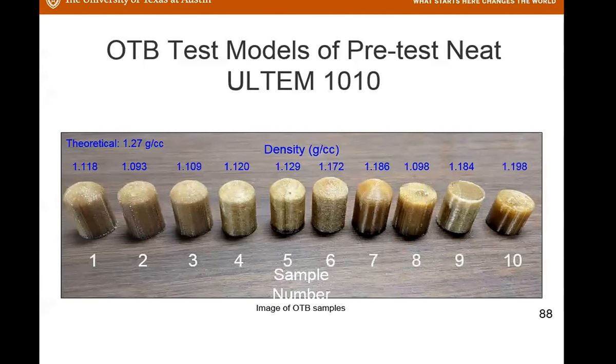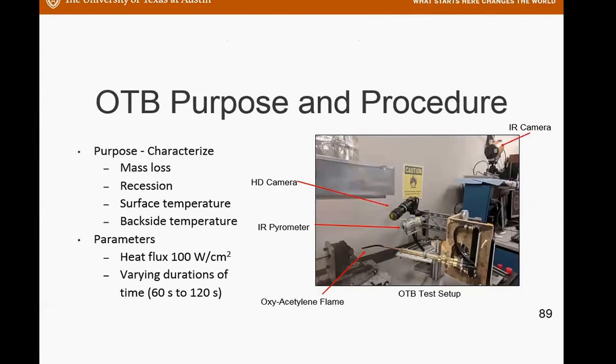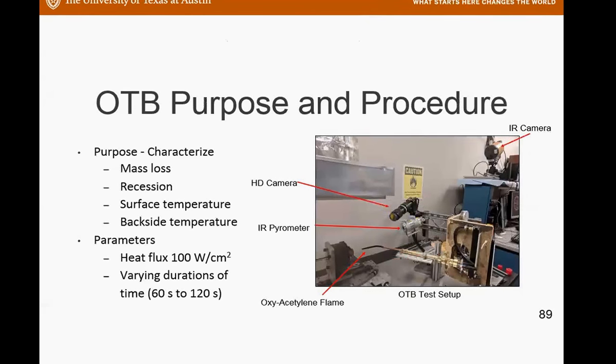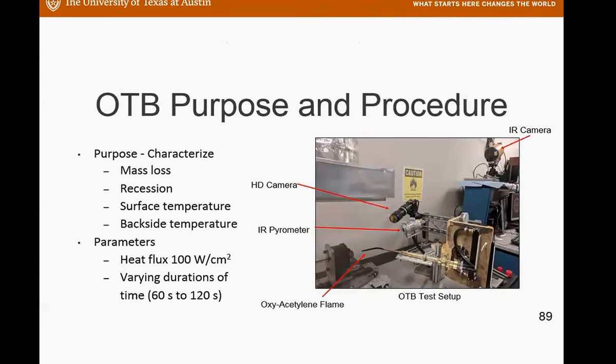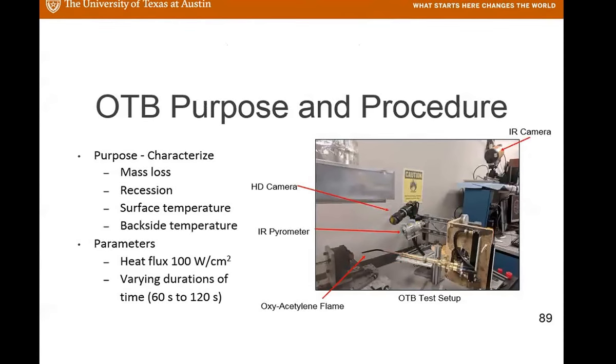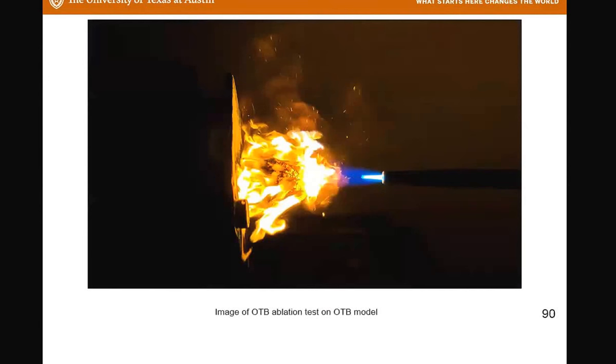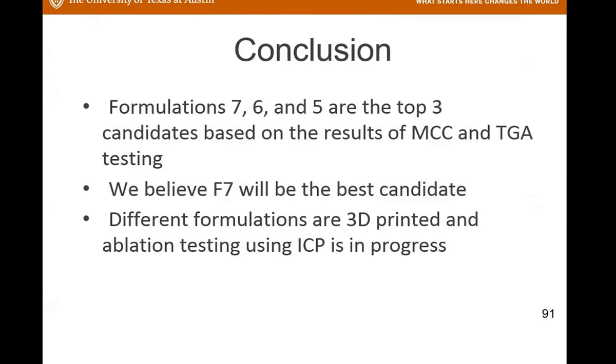They send it back to us. We measure the water displacement and see what the density is. The one with high density basically does not pass the requirement. And we also have equipment that uses an IR camera and a high definition camera. These are actually on loan to us forever from NASA. And 2 color pyrometers, and we have the oxygen flame and test all these. And this is a test during one of the tests that we did.